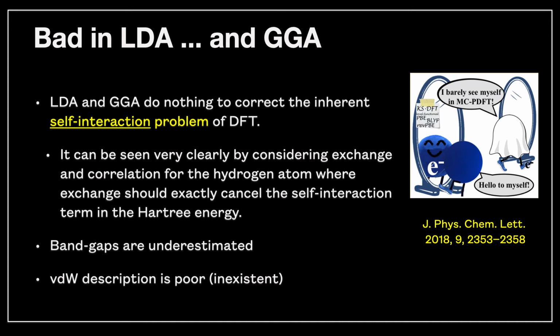So we will discuss also in a few minutes that LDA seems to be working in some instances for van der Waals, but it's purely coincidental, from the cancellation of errors, because LDA does not include anything about van der Waals interaction. And actually GGA usually fails completely in describing van der Waals. In fact, very often GGA is repulsive for van der Waals instead of having a local minimum. We'll discuss that in more details.